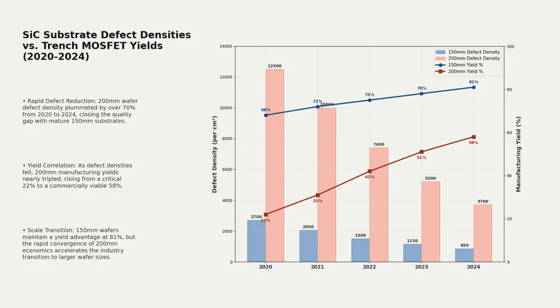These defects, primarily threading screw dislocations, compromise the physical structure of the wafer. During high aspect ratio reactive ion etching, these dislocations concentrate electric fields. This causes localized gate oxide breakdown at voltages up to 30% below rated capacity. Consequently, manufacturing yields for 200mm trench devices remain suppressed at 58%. This is far below the 80% threshold required for stable, low-cost commercial volume production.